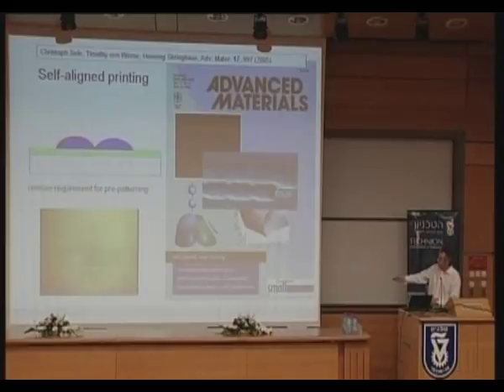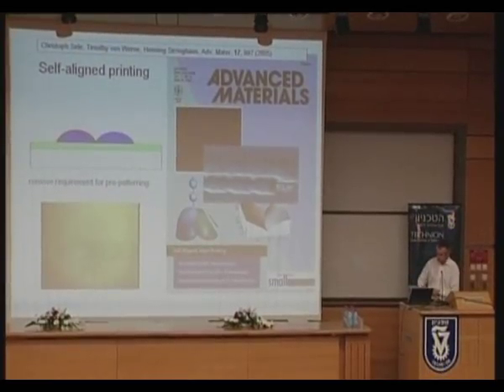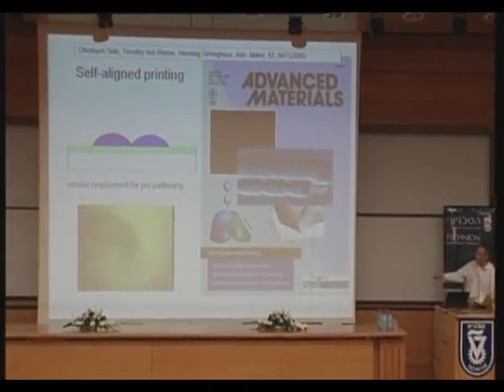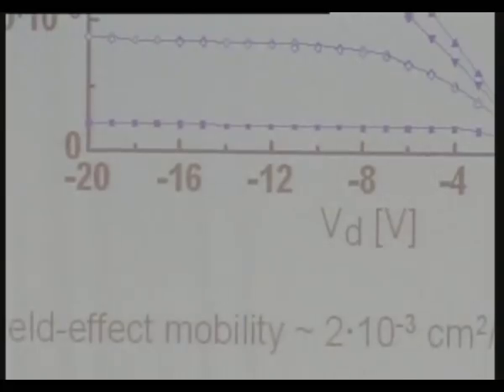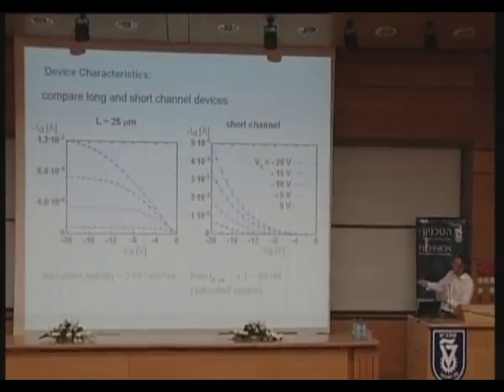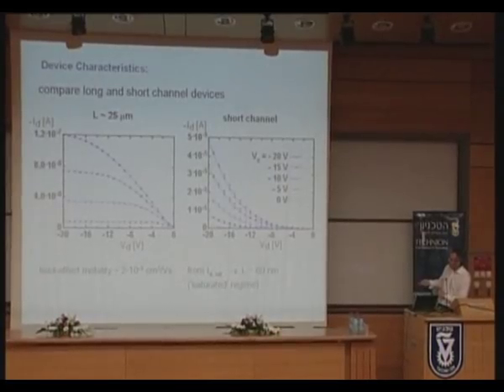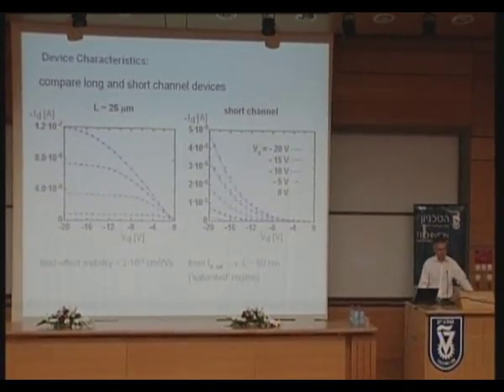What you can see there is a first set of drops that has been printed to form a line, and then what is being done is to print a second series of drops, and they're just repelled away from the first track. And remarkably, they don't short, they're pretty reliably insulating. And then if we make transistors, the inferred channel length for these structures is about 60 nanometers. So 60 nanometers is current Pentium technology. We've done that, if you like, without any brute force lithography, and we can do that over a large area.